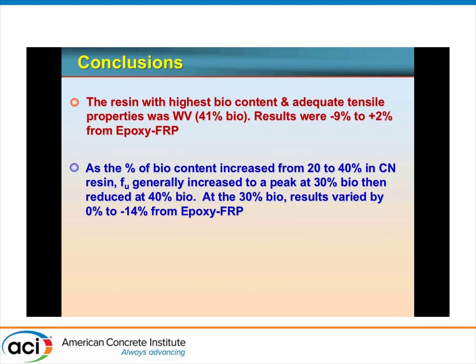As the percent bio content increased from 20 to 40% in the CN type, that's the cashew nut based resin, the tensile strength increased until a peak at 30%. So 30% was the highest value, then it reduced when we went to 40% bio. At that peak of 30%, the results varied from epoxy by 0 to -14%.